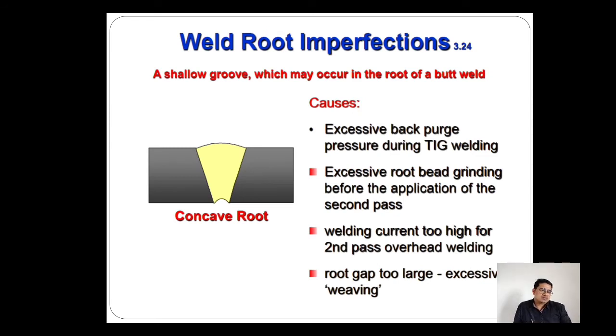But this is the concave root. Basically, concave root is a shallow groove which may occur in the root of the butt weld. The main reason for concave root is excessive back purging pressure during TIG welding. When the welder is performing the GTAW process, you know that the welder applies back purging with argon gas from the back of the welding side, and sometimes the pressure of the argon gas cylinder is high, so such a problem may happen.